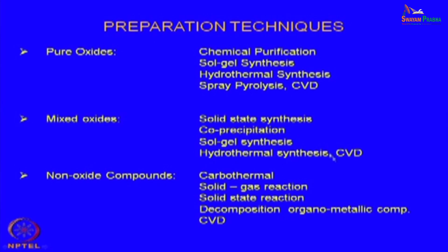Once again, in all these things, because these are non-oxides, oxygen has to be excluded. The presence of oxygen should not be there, and therefore, that is an important criterion, that whatever you do here, whether it is a solid state reaction, solid gas reaction, carbothermal reaction, decomposition of organometallic compounds, this is another. So, whatever you do, you have to exclude oxygen. The presence of oxygen must be avoided to make non-oxide compounds, which is quite obvious.